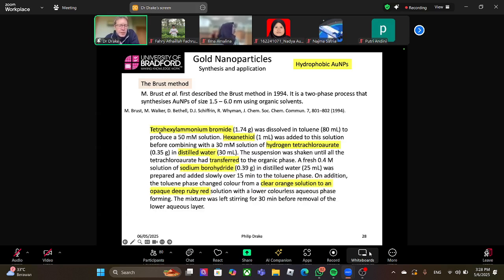You take a surfactant, tetraoctylammonium bromide in this case, that's dissolved in toluene. You add in hexane thiol, we'll talk about that in a minute as to why that's there. You add that to solution. You combine that with an aqueous phase of gold tetrachloroaurate. So it's the same source of gold, hydrogen tetrachloroaurate in water. This gives you two phases, toluene phase and aqueous phase. Shake them and mix them, you'll see the tetrachloroaurate transfers from aqueous into the toluene phase.